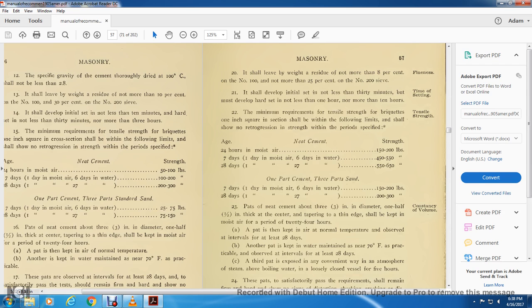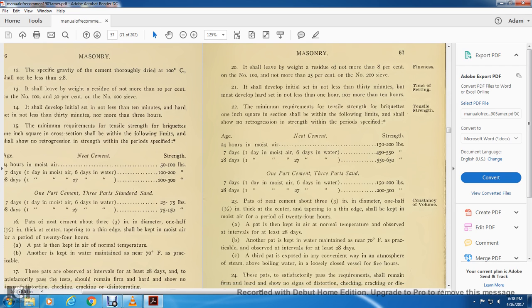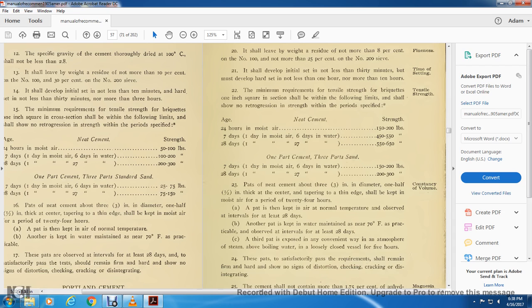24 hours in moist air, 50 to 100 pounds. 7 days, 1 day in moist air, 6 days in water, 450 to 550 pounds. 28 days, 1 day in moist air, 27 days in water, 550 to 650 pounds. 1 part cement to 3 parts sand: 7 days, 1 day in moist air, 6 days in water; 28 days, 1 day in moist air, 27 days in water, 200 to 300 pounds.